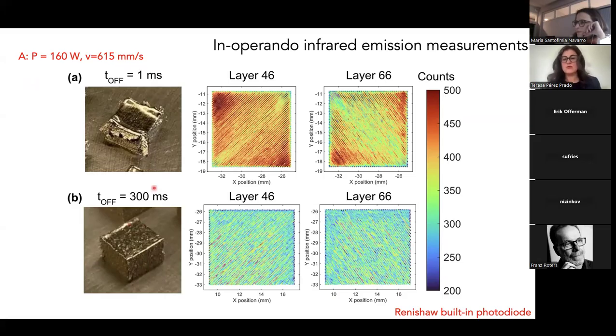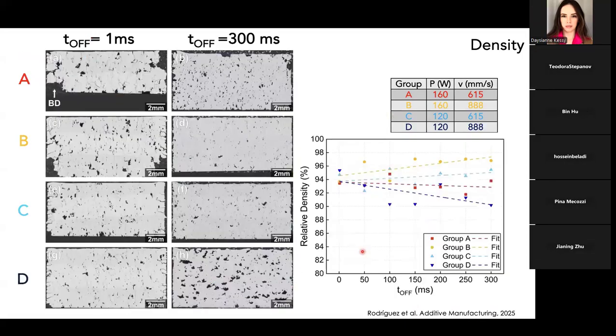But let us see what we have inside. And here these are just 2 emission maps measured by a built-in photodiode in the chamber. This is infrared emission. And this corresponds to layers 46 and 66 in both samples. So you see, of course, that with the introduction of the time delays, there is less heat, less emission, which was the goal. But let us see whether this serves our purpose. This is what's coming next.